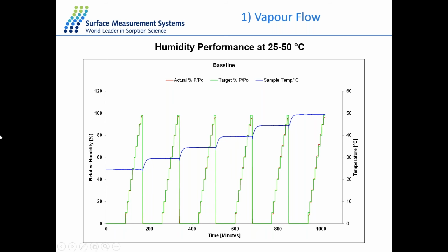So for example, the generation of humidity at 25 to 50 degrees, we generate the humidity from 0 to 90% RH. The red line is for the actual or measured value for the partial pressure, and the green line is the target value we want to generate. And the lines are just overlapping here. That means the 2 values have very good agreement with each other. And here just shows the system has a very excellent humidity performance within a long time, like over 24 hours or even longer time.